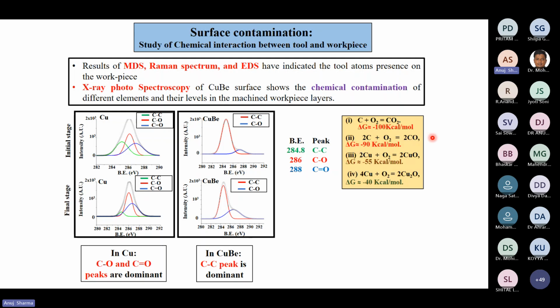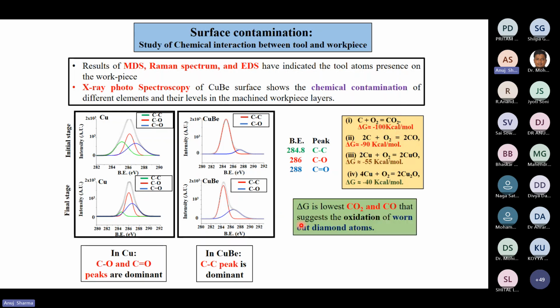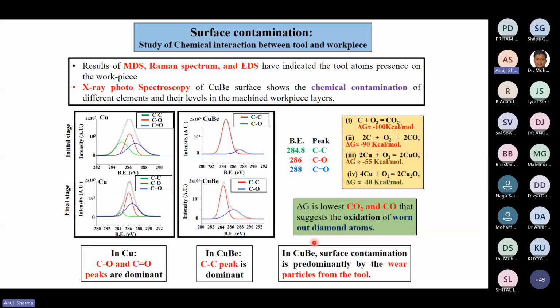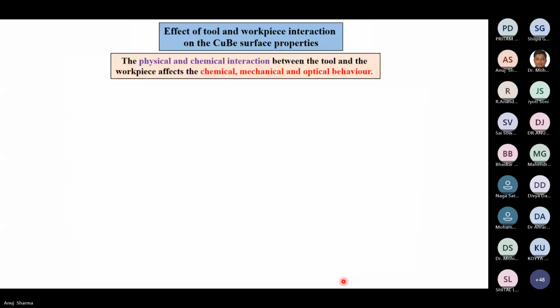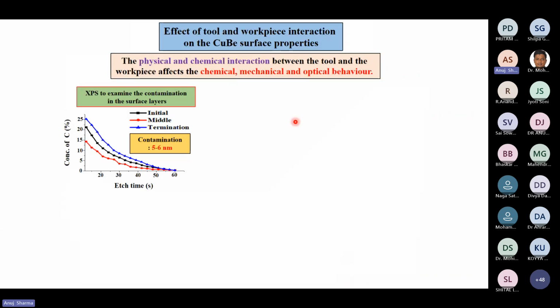So basically the oxidation of the diamond tool on the workpiece is taking place. Delta G is lowest for carbon dioxide and carbon monoxide. So that's why the oxidation of these worn-out diamond atoms is taking place on the workpiece. And in copper beryllium, the surface contamination is mostly from carbon-carbon bonds, which are just the wear particles from the tool. This physical and chemical interaction between the tool and workpiece also affected the chemical, mechanical, and optical behavior.